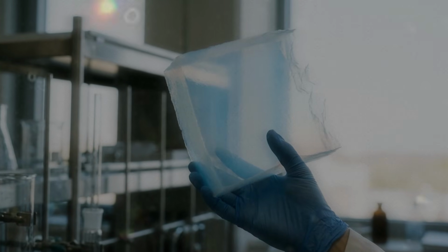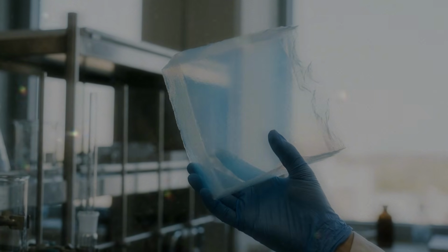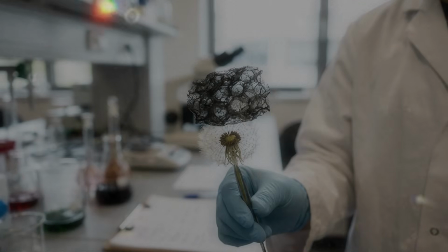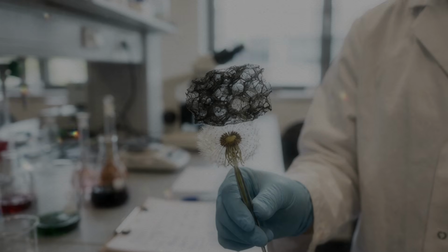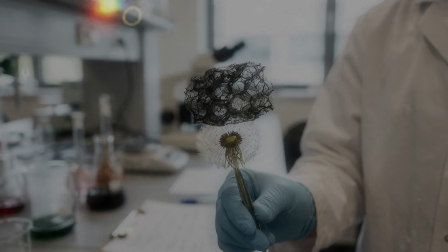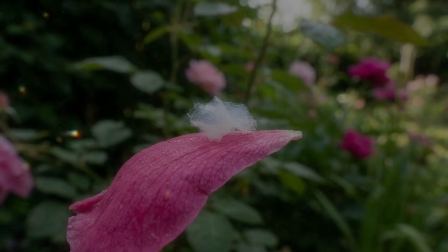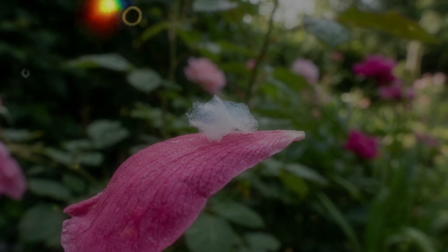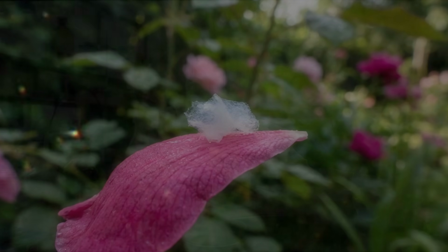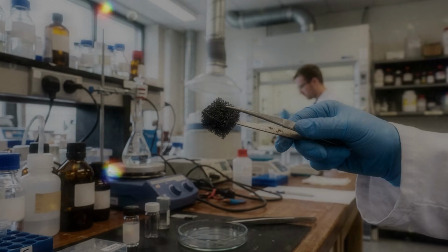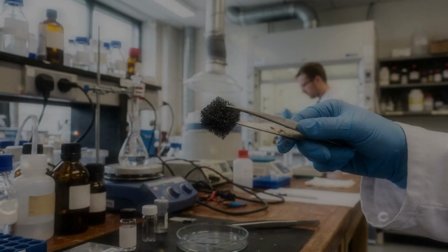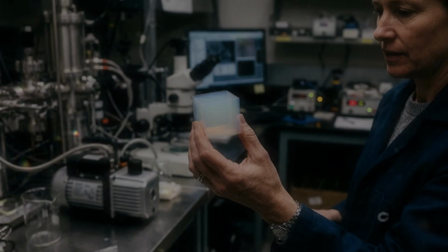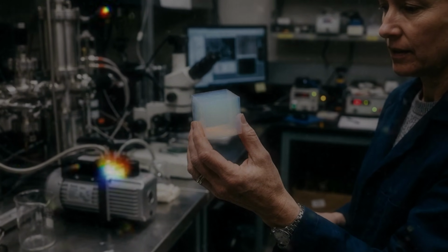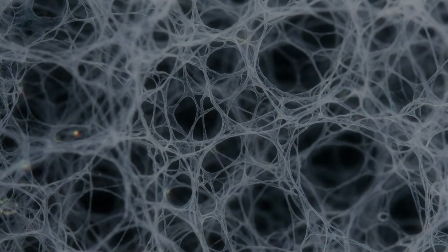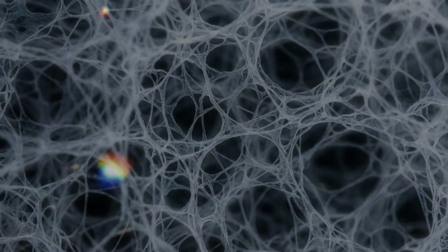For a useful sensor, the response must be predictable. The same amount of pressure should produce roughly the same signal each time. The material should recover quickly. It should not become permanently compressed after a few uses. Temperature and humidity should not create confusing changes. These requirements are much harder to meet than simply proving that resistance changes under pressure. Laboratory demonstrations can show that a material is sensitive. Practical devices must also show stability, repeatability, durability, and a way to connect the delicate aerogel to ordinary wires.